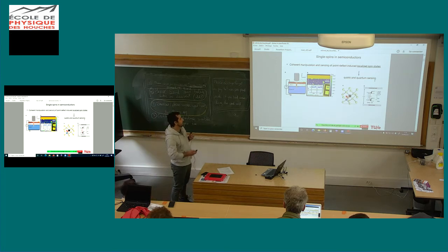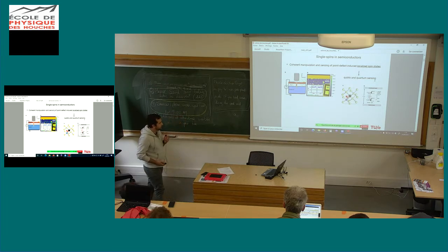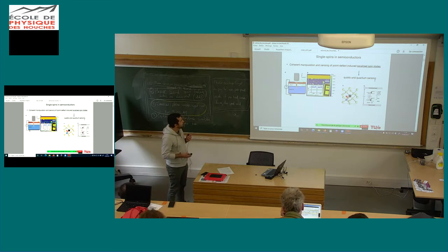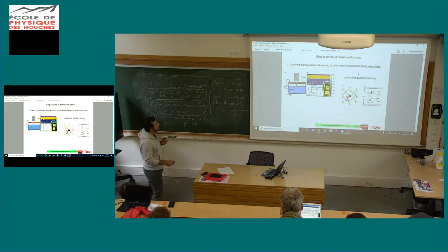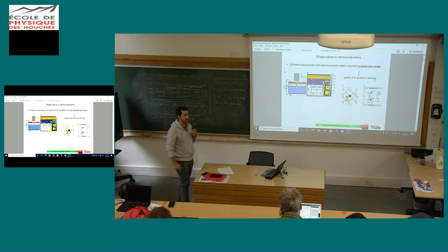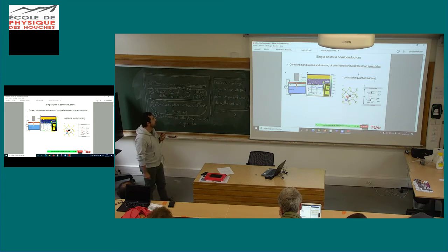So, coherent manipulations and point defects in semiconductors. This is a field that has developed quite a lot in recent years. We already have some industrial applications. Just to give two examples, on the left we have silicon carbide, and on the right diamond. In diamond, these are called NV centers. It's basically two defects, one substitution of nitrogen close to a vacancy in diamond. These states are used in quantum sensing, so they provide a very good nanoscale magnetometry system, and it's similar in silicon carbide.